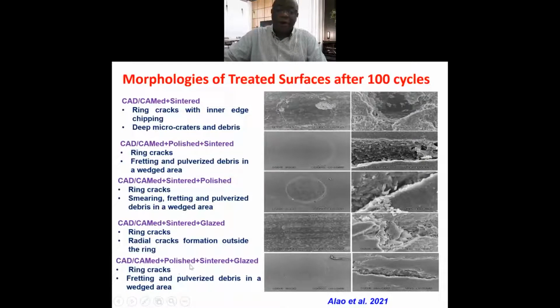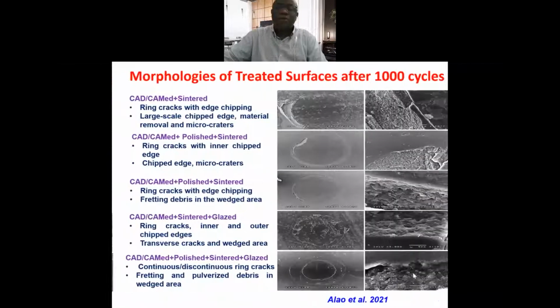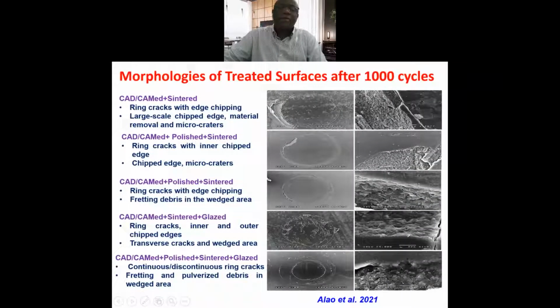So for the CAD-CAM polished sintered glaze, you can see the ring cracks, then fretting and pulverized debris in a wedged area. Then after the 1000 cycles, you can see here the ring cracks but with edge chipping. You can see large scale edge chipping, material removal, and craters. So for the CAD-CAM polished sintered, the one that we propose, you can see the ring cracks with inner chipped edge and micro craters.